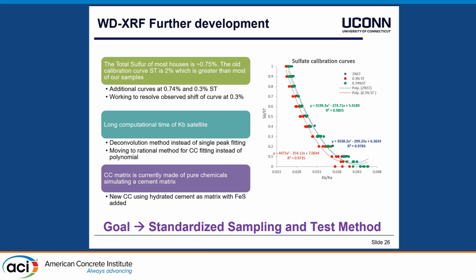In terms of the WD-XRF, there's a whole calibration method development behind this, and it always needs to be fine-tuned further. But in the end, you can see certain calibration curves indicating sulfide to total sulfur ratios, sulfate to total sulfur ratios. The goal, in general, is to standardize in the end the sampling and test method to test for sulfides and sulfates.